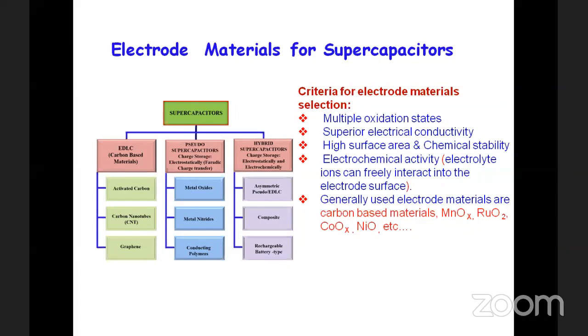As I told you earlier, we have EDLC, carbon-based material, and in the pseudo supercapacitors, the charge storage is done through Faradaic charge transfer mechanisms. Therefore, in all the cases, mostly metal oxides, metal nitrides, and conducting polymers are very promising. In fact, such materials have been found to show much better supercapacitance than the EDLC type, which are all carbon-based. Why is EDLC also interesting? Mainly because the surface area to volume ratio is fantastic, and carbon material has excellent electronic conductivity also. All these factors make EDLC a very interesting material.